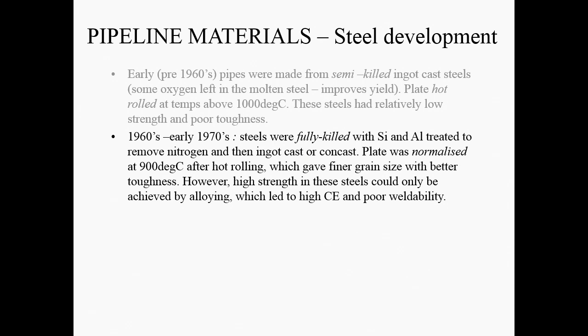So by the 1970s, we got steels probably that were strong enough for what we needed, but they were much more difficult to weld. And in this country, the 1970s was the expansion of the offshore, North Sea oil and gas. So a lot of these materials went into subsea pipelines. And that caused problems with weldability and things, and you had to work quite hard to make sure the quality was very good. So there was a driving force for improvement.